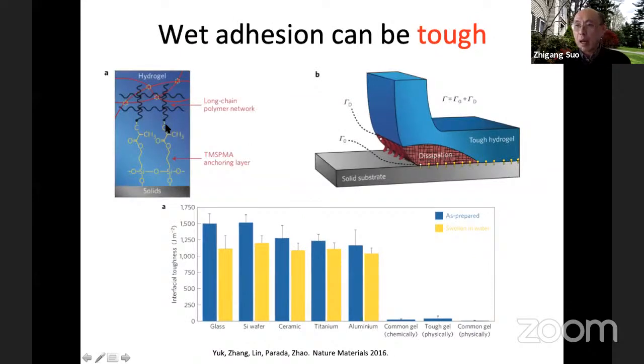You cannot rely on water to have strong adhesion. You really need to engage the polymer chain. So if you form a covalent bond between the polymer chain of the gel, the hydrogel, and the substrate, then this bond is at least as good as the gel itself. And we already know the gel itself is stretchable, right? Then this interface will be good enough, right? So that's one idea they had.